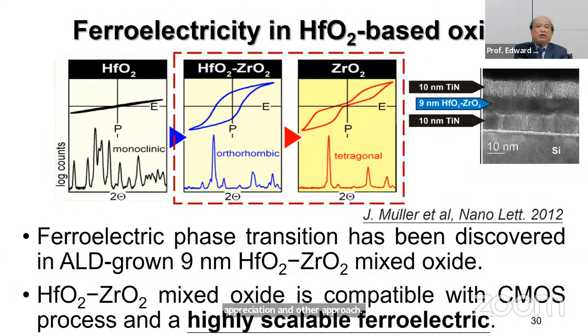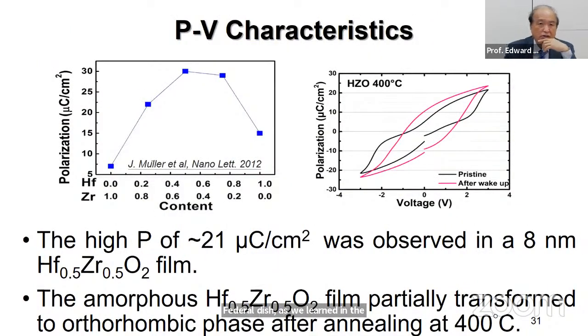So this is ferroelectric. What is the material? It's mostly hafnium oxide and zirconium oxide mixed. And this is not new, because this material is used in memory. So it's compatible with silicon CMOS application and is a very highly scalable ferroelectric, as we learned in the past. And when the hafnium oxide composition is 0.5, which is 50%, you can see very high polarization. If you have 8 nanometers, the polarization is 21 microcoulomb per centimeter square.